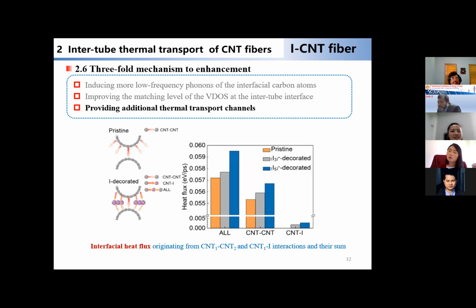The next is that iodine chains provide additional thermal transport channels. We further calculate the interfacial heat flux originating from tube 1 and tube 2, and from tube 1 to iodine filler interactions, and their sum. This suggests that the CNT tube and iodine interactions indeed facilitate the interface transport, which also confirmed that iodine chains provide thermal transport channels between tubes.